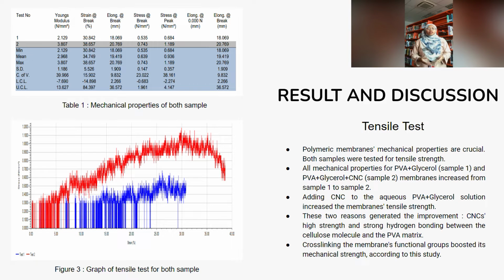According to what is shown in the table, the mechanical qualities improve from sample 1 to sample 2, for the membranes that contain PVA and glycerol in the first sample and membranes that contain PVA, glycerol, and CNC in the second sample. Because of this change in direction, the tensile strength of the membranes was improved by the incorporation of CNC as a filler into the aqueous solution of PVA and glycerol.